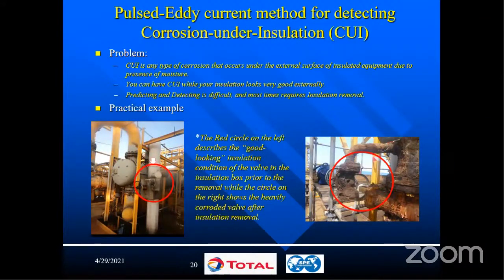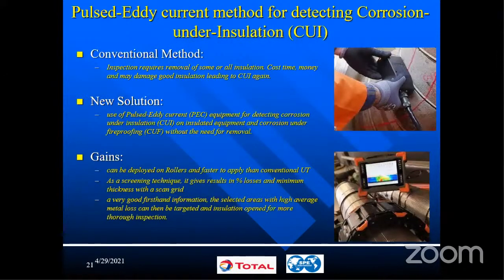So you can see a typical real life example on the picture on the left. You have this section of piping. The insulation looks like it's in good condition. But when the insulation was stripped off, you could see that already the pipe was completely gone. So insulation can look good, but the problem is existing beneath.